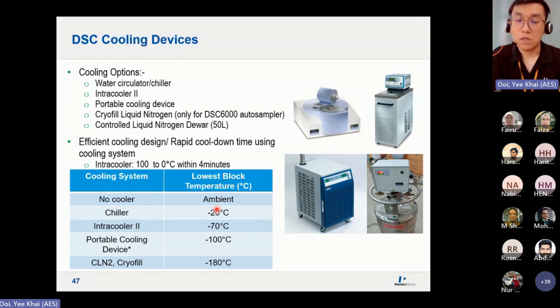Generally, we supply the Intracooler 2. You can start off at -70 degrees C, meaning you can start your experiment at -70. Then, of course, if you want to go all the way down, you can start at -180 degrees C using the Cryofill tank. It looks like this. This is a liquid nitrogen dewar tank. The whole thing is 50 liters, it can hold up to 50 liters of liquid nitrogen. So you can start your experiment at -180.